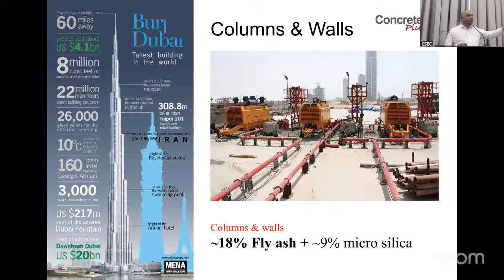Why is the amount low? Because the durability issues are not much there. Second, if you add more fly ash, strength goes down. So durability issues are not critical because they are at 18%, 18 plus, which means durable. But you need to have a certain strength. Strength is the critical one. This is for all the columns and all that. And you should be able to pump the concrete.